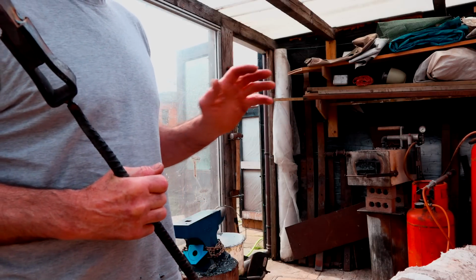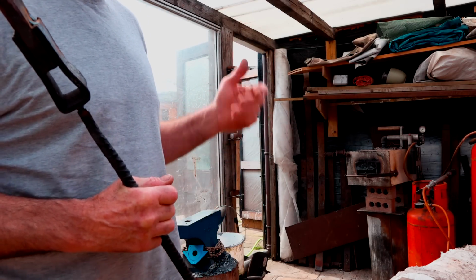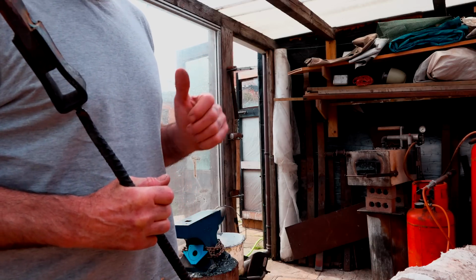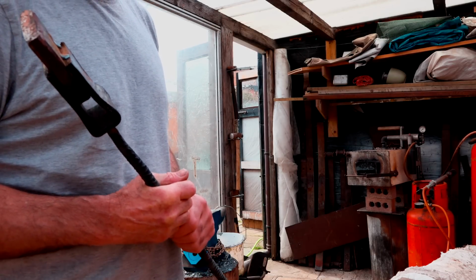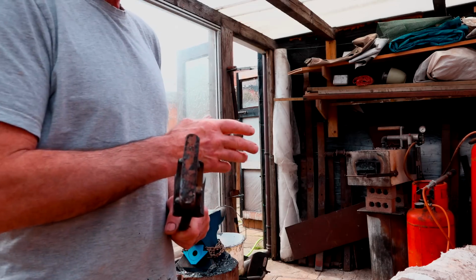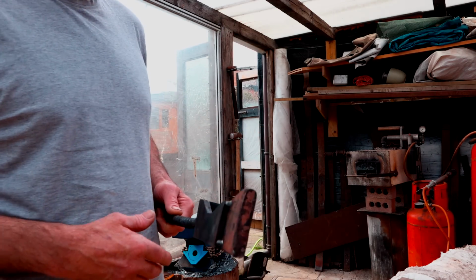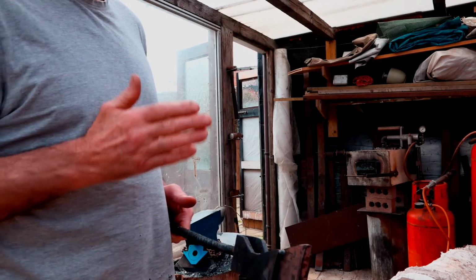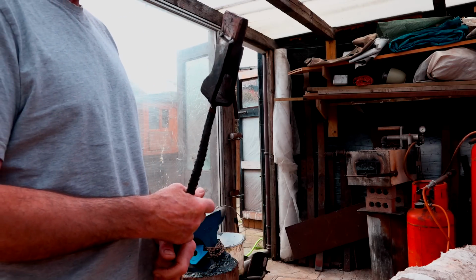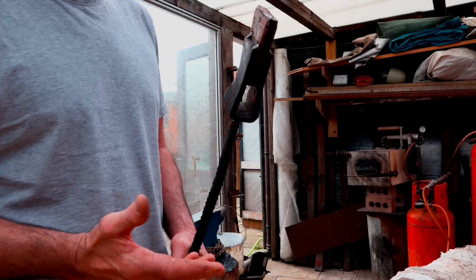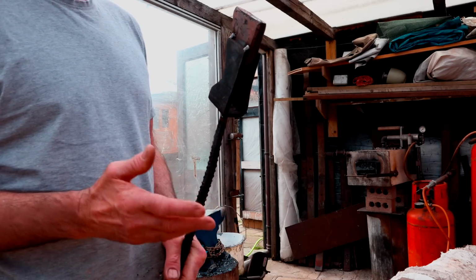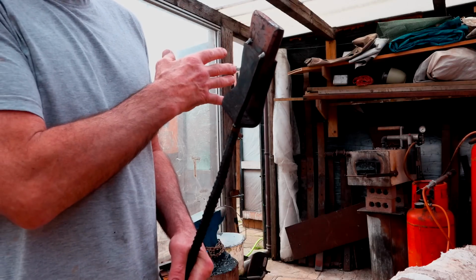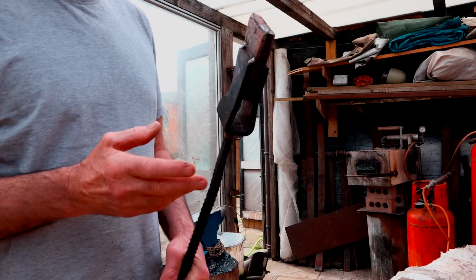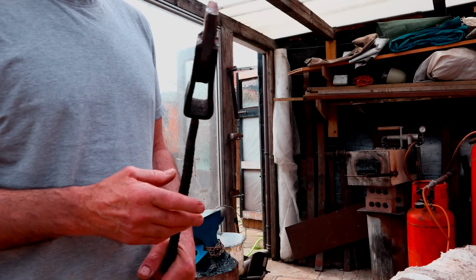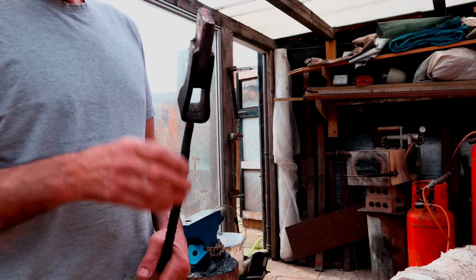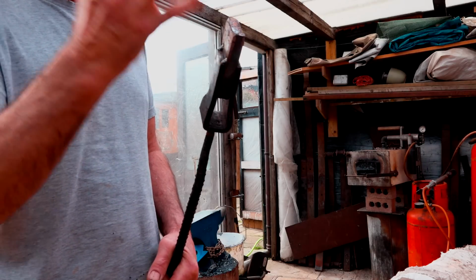Forge wise, heating the steel is probably a subject on its own, but I use a gas forge, as you've probably seen. I like the gas forge because it won't overheat the steel, and I can control the temperature, and I don't have to mess about with fire. The steel goes in and comes out. This little forge runs between 1300 and 1400 degrees centigrade, which is perfect for welding steel together. I have tried coke and coal and charcoal forges before I set up with this gas forge, and fair enough, coke and coal forges do get the steel a lot hotter, but it's also very easy to burn your steel. And by burn I mean literally burn. The steel will just go off like a sparkler and burn away to nothing.